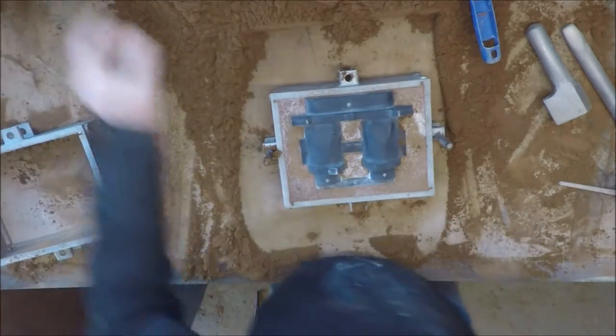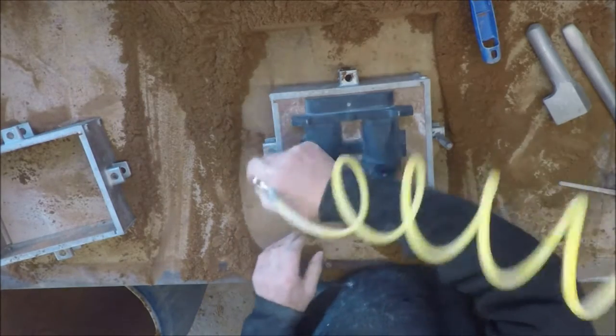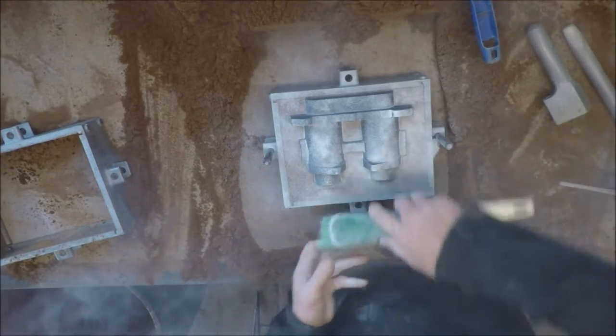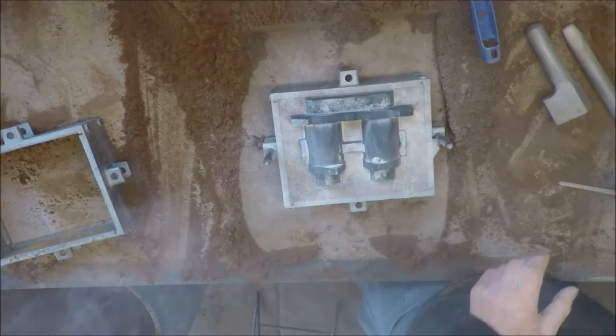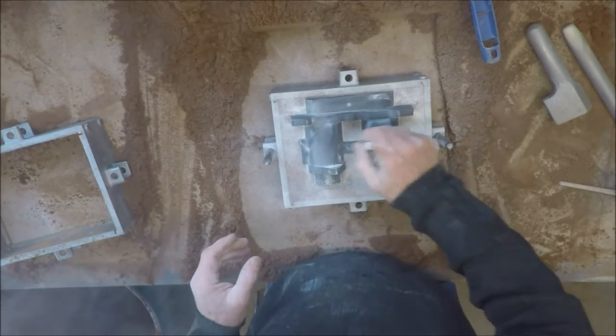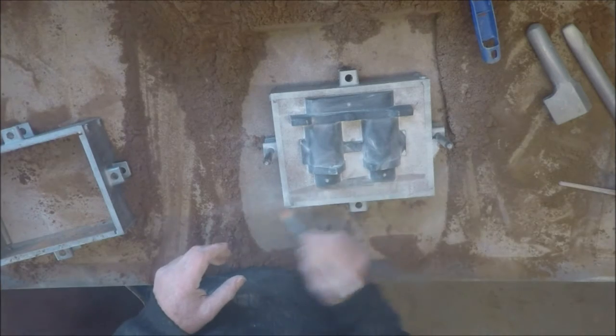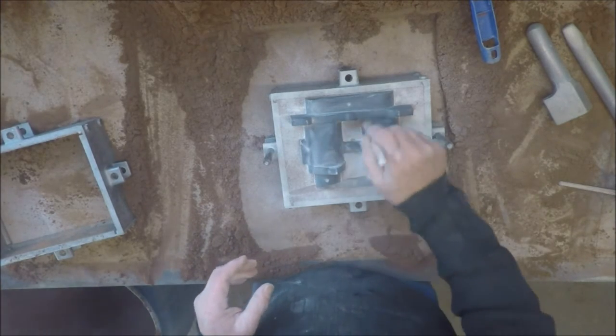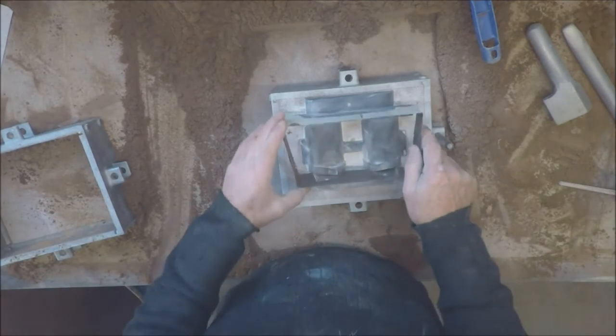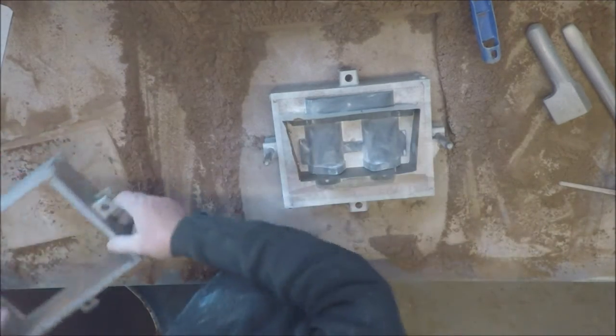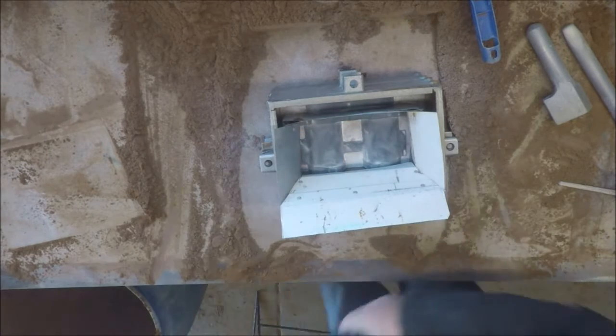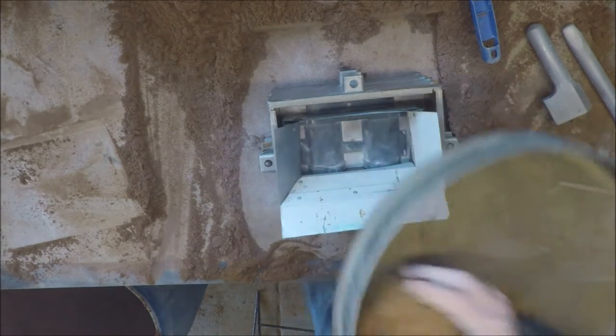Remove the odd side. This parting agent incidentally, it's a commercially purchased one. It is in fact calcium carbonate, very finely ground limestone, nothing more. It's much better than talc. I know some people do use talc, but talc costs you about ten dollars a kilo. That limestone was three dollars a kilo. More facing sand.